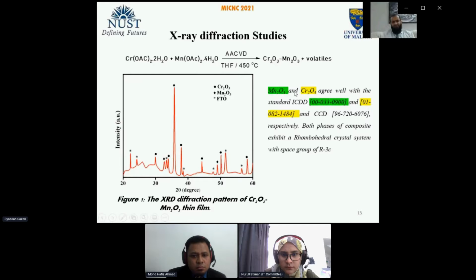The very first characterization technique was XRD. The XRD confirms the manganese oxide and chromium oxide, which are in a good match with the standard ICDD card numbers. These are available here, and this confirms that this is the impurity-free chromium manganese oxide thin film.